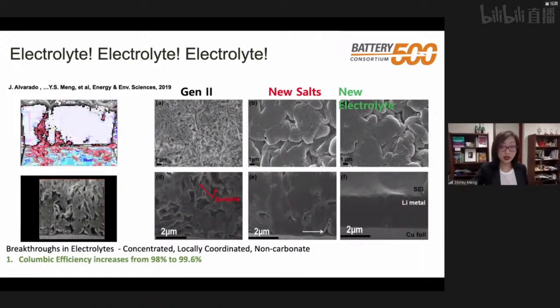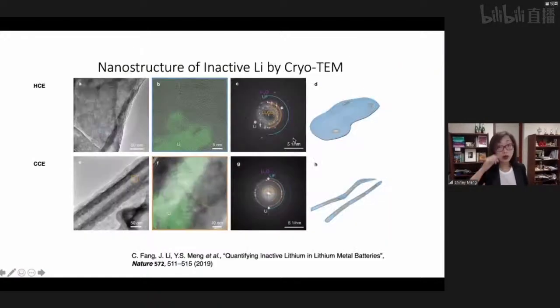So in order to understand why morphology is so important, I want to show you this TEM picture, and it's obtained under cryo condition. You cannot obtain this kind of very high resolution image in a regular TEM because these metallic lithium are surrounded by the insulating SEI. SEI contains lithium oxide, lithium fluoride, lithium carbonate. It's very insulating. So when you put a high energy electron beam on it without the cryogenic condition, it's not just the temperature; cryo-TEM also uses very low dose and very high detection efficiency detectors, right?